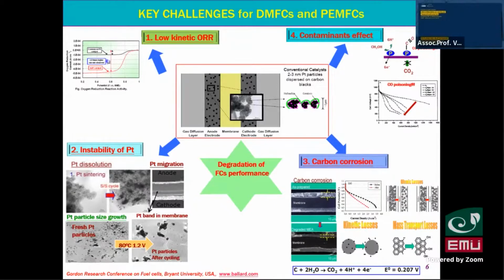And the fourth, last issue is the contamination effect. If we use methanol or ethanol, with oxygen supplied at the anode, we can get CO poisoning. This CO poisoning gets absorbed onto the platinum catalyst, which affects the activity of the platinum catalyst. So this is the main current issue in methanol and ethanol fuel cells.